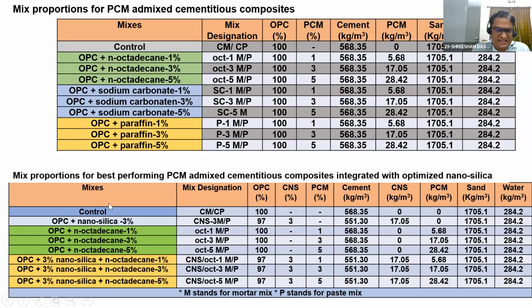So in the second stage, I have reduced my mixes to only n-octadecane: OPC plus n-octadecane 1%, 3%, and 5%, which I have already done. For all these three mixes, I have added 3% of nanosilica, because in one of our studies, we realized 3% nanosilica is giving the optimum mix.